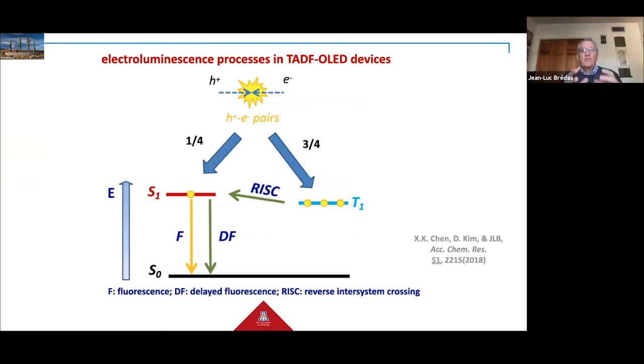And the idea here is to design organic molecules that have a lowest triplet state very close in energy to the lowest singlet state, within 0.2 eV or less. In that instance, during their lifetimes, the triplet exciton, through thermal excitation, can do a reverse intersystem crossing, go to the singlet manifold and produce a delayed fluorescence signal.